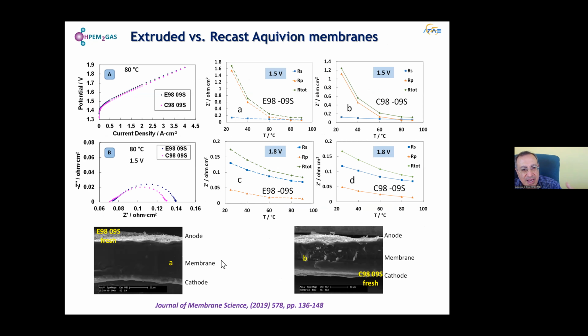Of course, you have different approaches for preparing a membrane. You can have cast or extruded membranes. Here are some pictures of the MEA, and you can see not much difference in polarization resistance, and similar variation of total resistance with temperature.